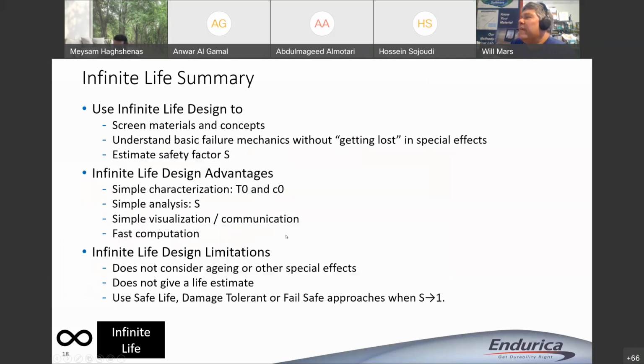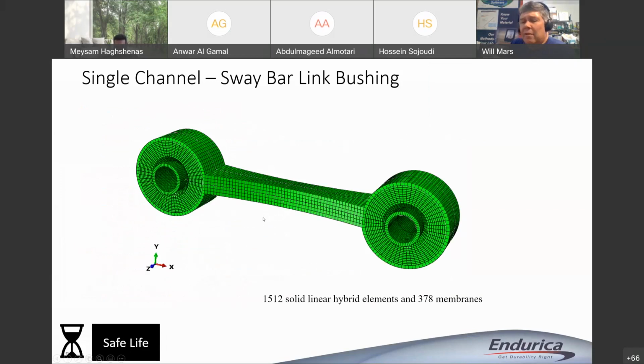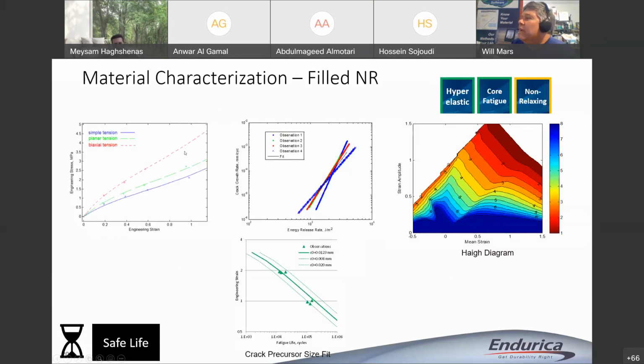Right, so that's a little bit about the infinite life approach. Here is the sway bar link. And we're going to do a safe life analysis on this. So here's an example of the material characterization we might do for this, right? So we have stress strain curves, we have fatigue crack growth rate curves, we have a crack nucleation curve. From these 3 pieces of information, we can computationally generate rubber's Haigh diagram, which is a map showing how the fatigue life depends on the applied mean strain and the applied strain amplitude. That's the materials characterization that we would do.